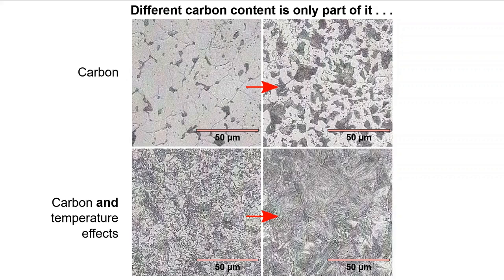As shown in the bottom left, under equilibrium conditions, a pearlite-rich structure is obtained with potentially some pro-eutectoid cementite forming. If the same composition is cooled fast enough, then the metastable martensite phase is obtained instead, as shown in the bottom right.